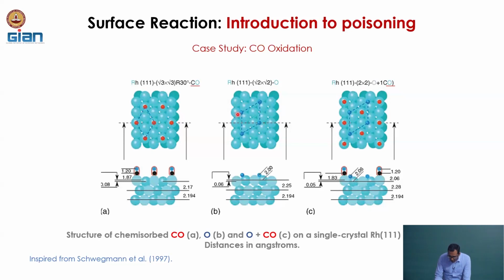Now, if we look at this diagram where both CO and oxygen are adsorbed, as you can see, if the surface is covered with CO, not exactly fully, but to a significant extent, then for the oxygen to be adsorbed on one site and then get dissociated and transferred to the other side, such that the two oxygen atoms after dissociation can take up two places, it has to go through a nearby CO species, and that is going to be energetically hindered.